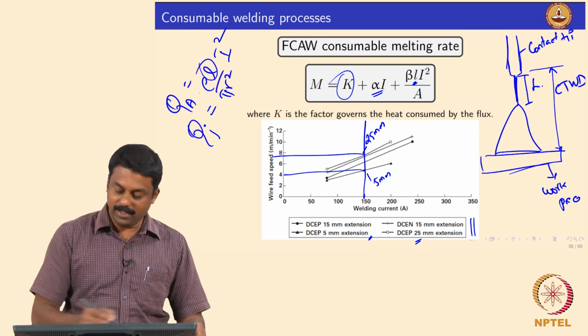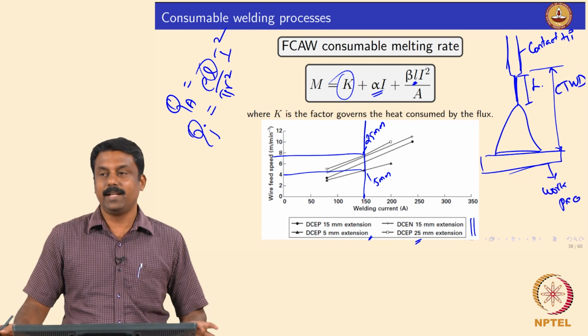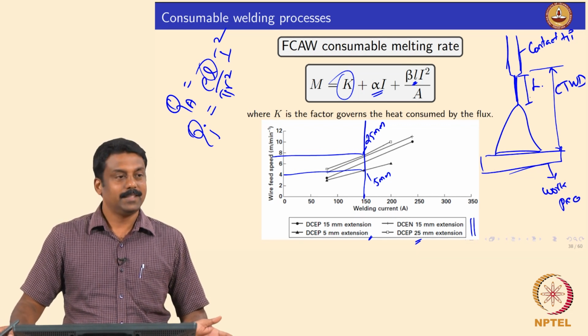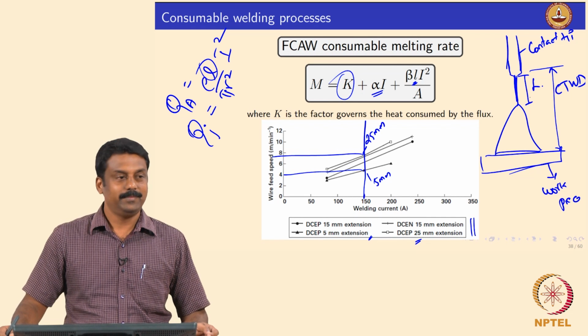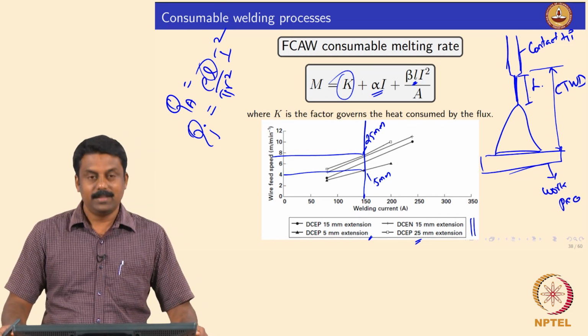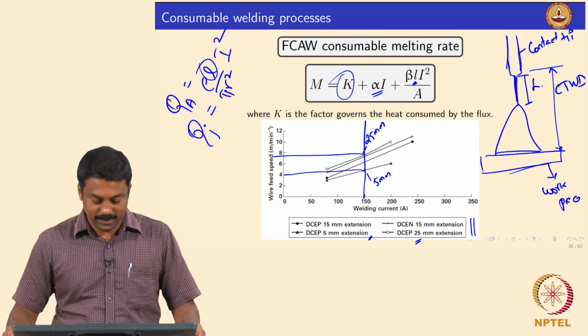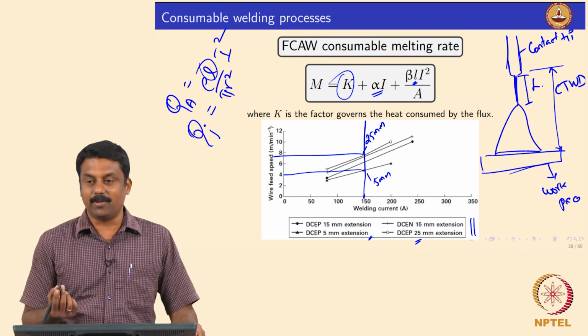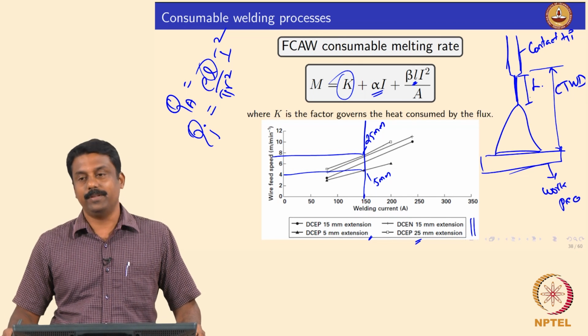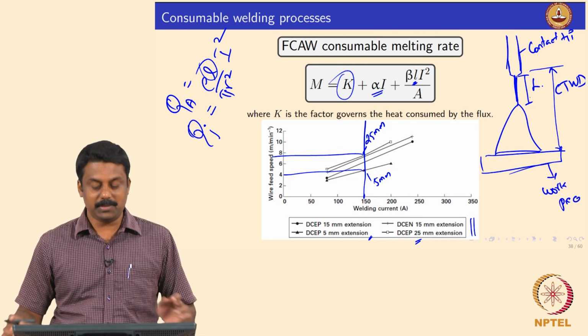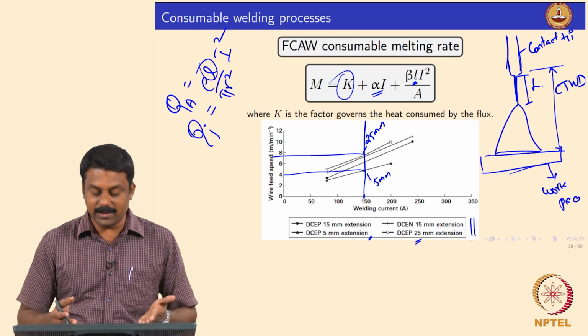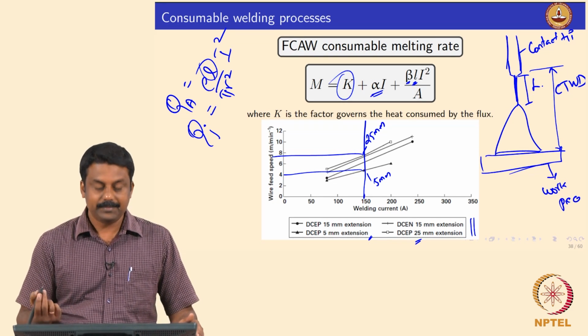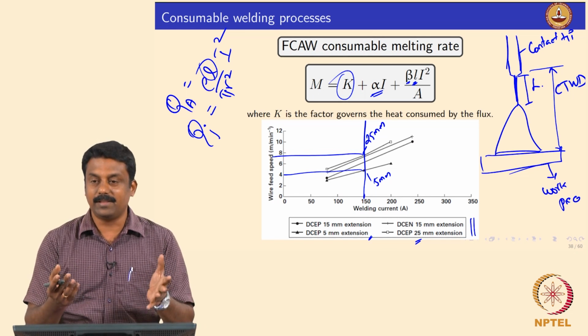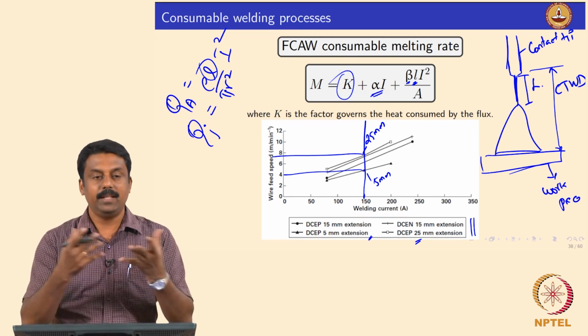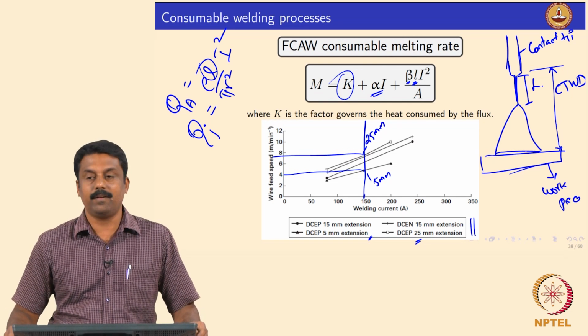So, what is L here? L is this stick out length. So, the more the stick out length, the more Joule heating, then more heat is there for melting, right. So, it is again the heat balance that we derived. So, by just changing the stick out length, you see that already the melting rate can be doubled, right. All other parameters in this equation are fixed, that is why we take them as a constant, because the process efficiency depends on the shielding gas, the characteristic of the ionization, the reactions, the heat generation which is happening.